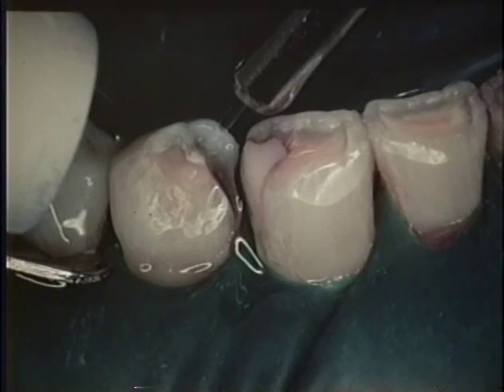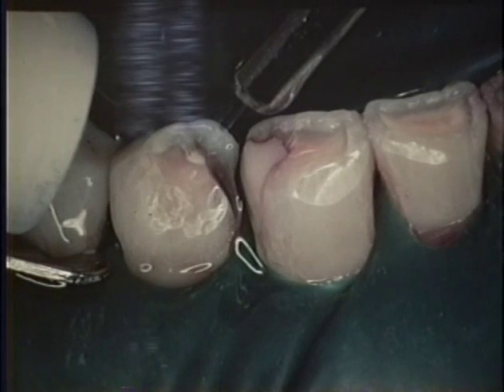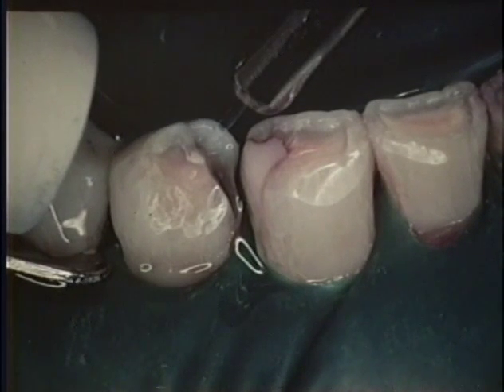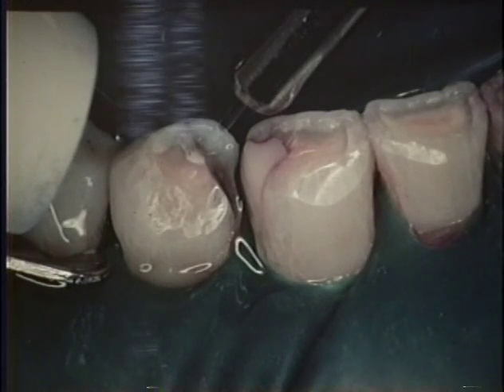Okay, go ahead and wash off all that phosphoric there. Wash off the salts from the chemical reaction, the phosphoric and the dentin and enamel. Now the phosphoric only decalcifies. It doesn't affect the collagen. So there's where we're going to start to diverge now. We can't do it today because of limited time, but certain bonding agents will in fact attach to collagen. Certain ones will penetrate through collagen, and certain ones would rather not have the collagen there. So you can deal with different bonding agents under different conditions.